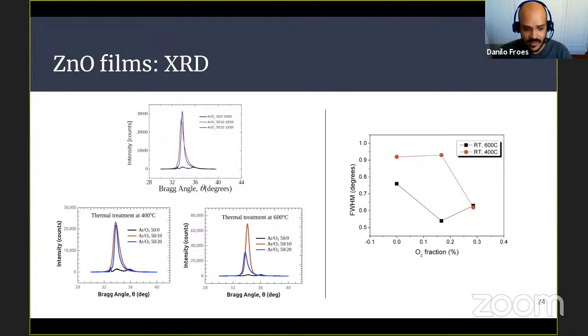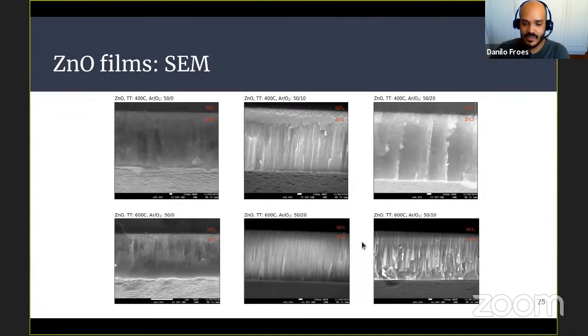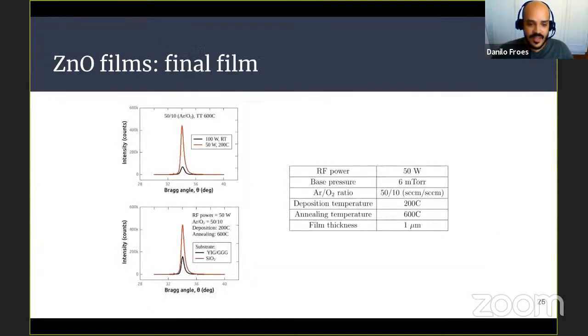Here we are depositing on a silicon substrate, SiO2 substrate. We added thermal treatment and varied the oxygen proportions. Here is summarized for 400 degrees Celsius the full width at half maximum. This is what we had. We also did the cross section of the samples. Without oxygen, we do not have the grain orientation, but we start having it when we put some oxygen there. For our final film, we did the optimization. We turned the power from 100 to 50 watts, so lower power, so we could have more crystalline results. We also tested this on a GGG substrate, and we had good results compared to the literature using these properties. And we made a final ZnO film of 1 micrometer thick.